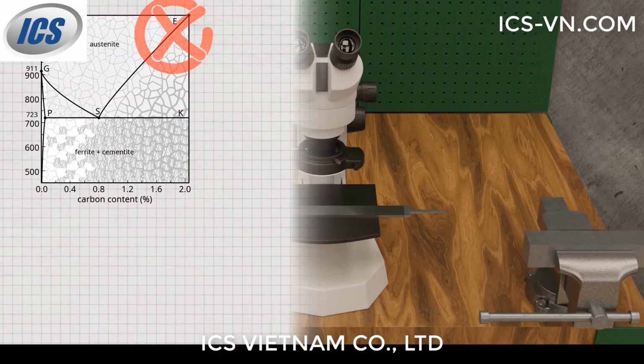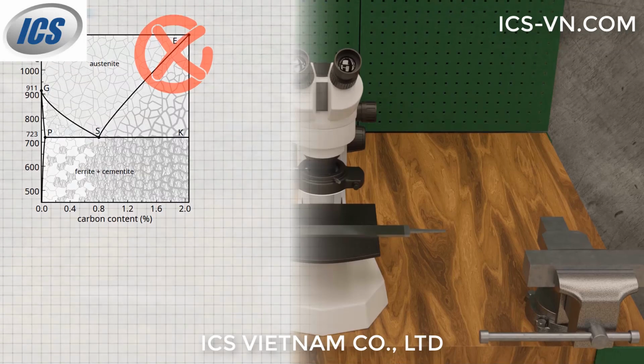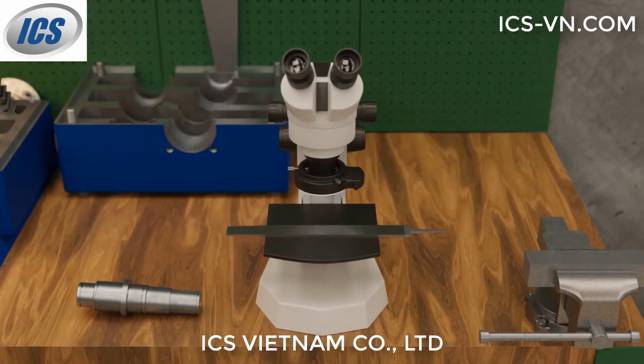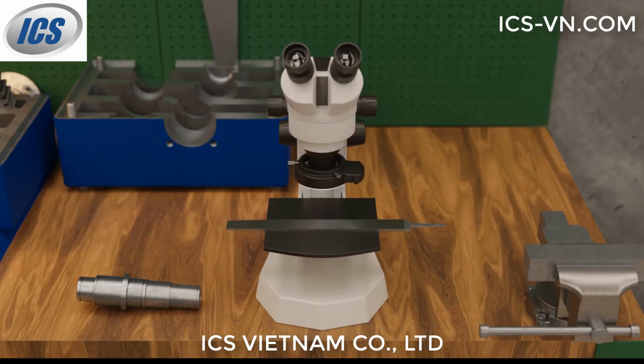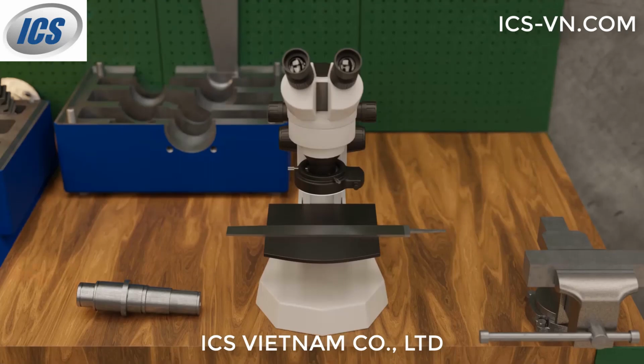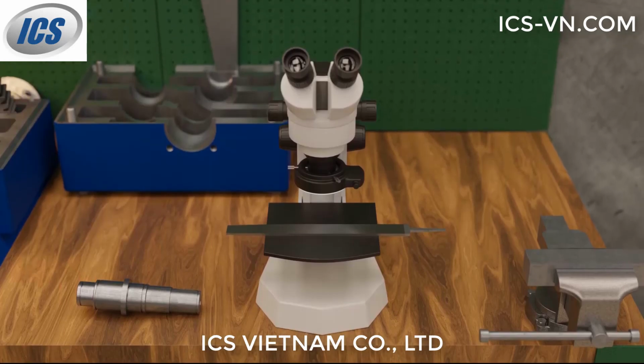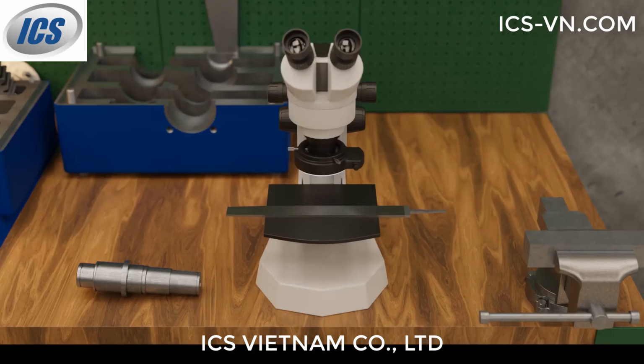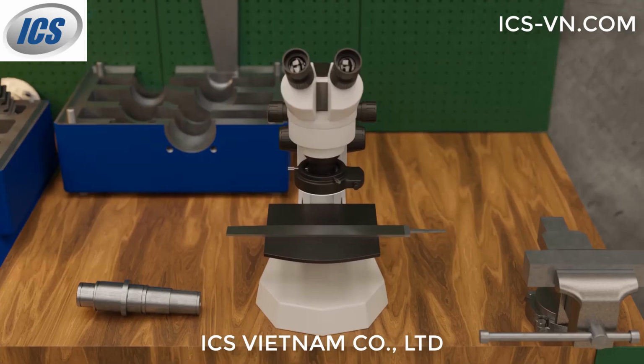A disadvantage of the high hardness and strength of the martensite microstructure is its enormous brittleness. Pure martensite has no slip planes and therefore cannot be plastically deformed. Especially in hypereutectoid steels, considerable embrittlement occurs due to the additional cementite at the grain boundaries. For this reason, hypereutectoid steels are often soft annealed beforehand.